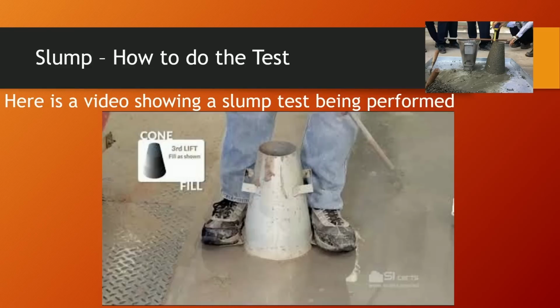We'll fill the cone in 3 equal lifts by volume, rotating the concrete around the mouth of the cone to evenly distribute. I'm going to rod this lift throughout its depth without forcibly striking the bottom. Half of my roddings are going to be at an angle to ensure that I get proper penetration into the corners. The rest will be across the cross section.